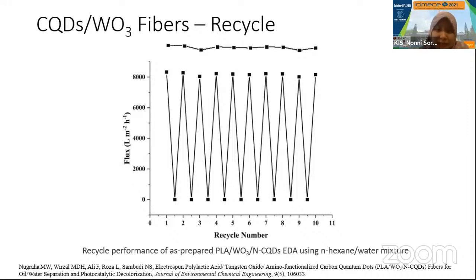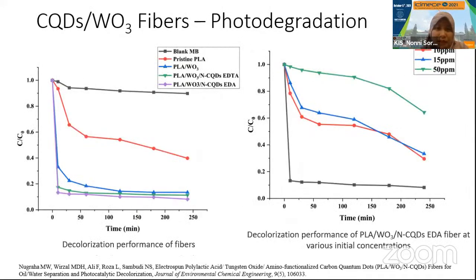Okay, right. So at the same time, we want to see whether, if we incorporate this material into the polymer fiber, the photocatalytic ability of this material is still intact or decreases. Okay. So again, we did the decolorization test. We use the same methylene blue solution. Okay. So this is for the 5 ppm performance. We can reach around 90% of the decolorization in less than 30 minutes. So meaning that the photocatalytic performance of the materials in the fiber is still intact.